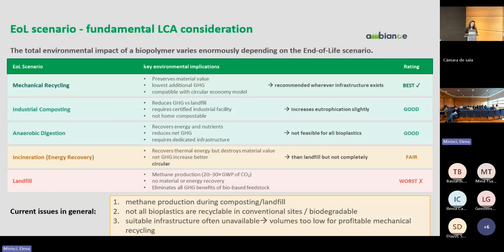Then we have industrial composting and anaerobic digestion that are better than the landfill but worse than mechanical recycling. The reason is that during the composting of the material, there are some emissions of GHG, some emissions of methane, for example. And also because they are less aligned with the principles of circular economy because they don't preserve the value of the product at the end of life. And then there is incineration, a standard practice where you incinerate the product in order to recover energy. The good aspect of this process is the recovery of the energy, but then you don't consider the value of the product itself because you burn it.